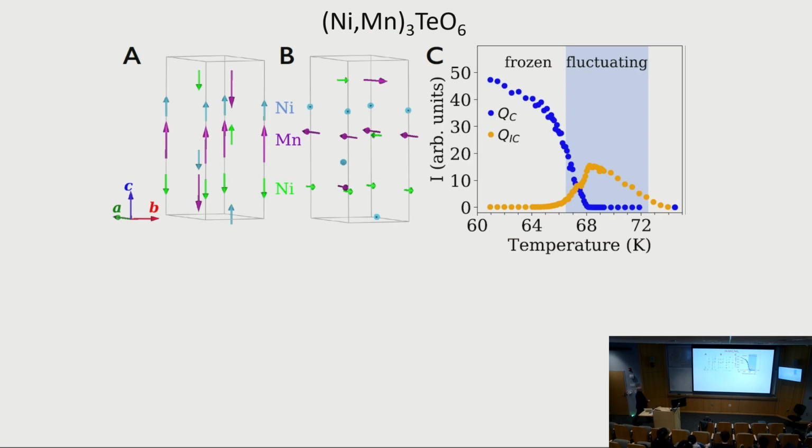Going back to the two magnetic structures observed in the manganese-doped nickel tellurate, I said that I was so far talking only about this state, which is a collinear state, and in this state only one type of phase domain boundary is allowed. This is the anti-phase domain boundary. Basically, what you do is switch the direction of all the spins. In a helical structure, however, different types of phase domains are possible. If the structure is commensurate, for example, let's say the period is 3 unit cells, right?